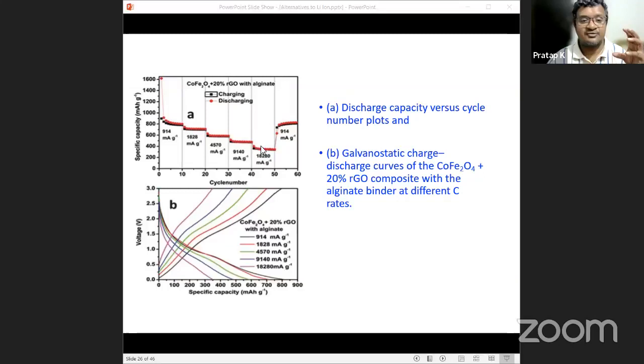Then what we tried to do was, again, give the same current which we applied initially. This is to check: look, we have increased the current, so is the battery damaged because of increasing the current? So then when we apply 0.1 C again, we gain the same capacity, 914 mAh per gram. And this shows that merely by increasing the current, your material is not damaged.